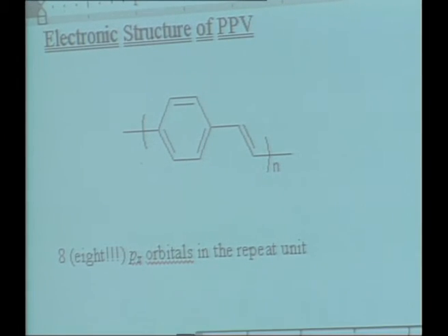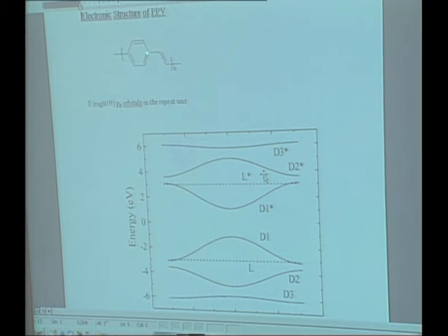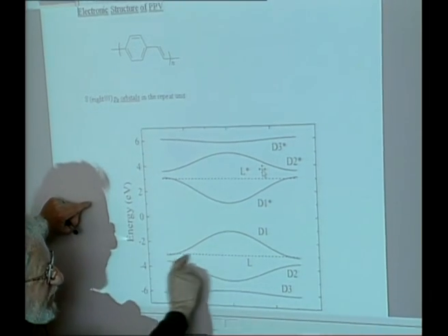Some of the bands are quite flat. It turns out, if you look at the quantum chemistry of that, the flat bands come about because of the wave functions of benzene. You just take benzene alone and calculate the molecular orbitals, you remember how this goes. There's a lowest energy one, 2 degenerate ones here, 2 degenerate ones here, and then a high energy one, six molecular orbitals, because there are 6 atoms in benzene. 2 of the intermediate energy wave functions have a node at this point. If there's a node at this point, then there's no way that the electronic wave function can delocalize past that node. And therefore, this band is truly flat, and this one is truly flat. It's flat for symmetry reasons, because there's a node in the wave function of benzene.